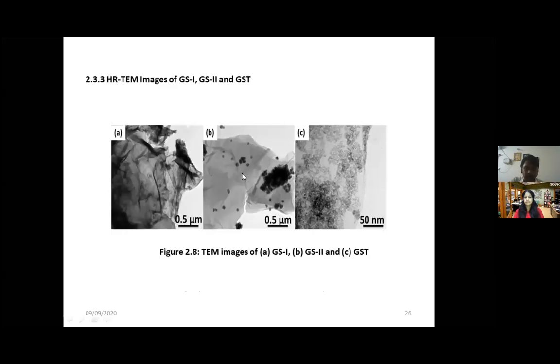This is for GS1, GS2 and GST. Here the tin dioxide is uniformly distributed over the graphene sheet. This is the graphene sheet that has been observed here. For GS1, the tin dioxide is uniformly distributed. For GS2, it has been agglomerated. If there is no graphene oxide, even in GS1 it will be agglomerated like this. Hence there won't be a large surface to volume ratio, and surface to volume ratio is important for the gas. If it is high, a greater amount of gas will get adsorbed, and the resistance changes accordingly.